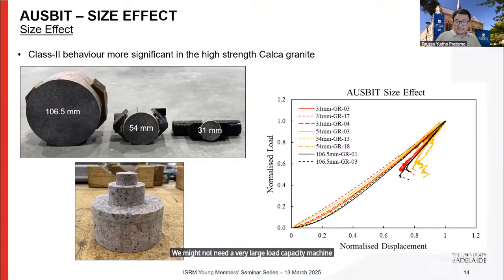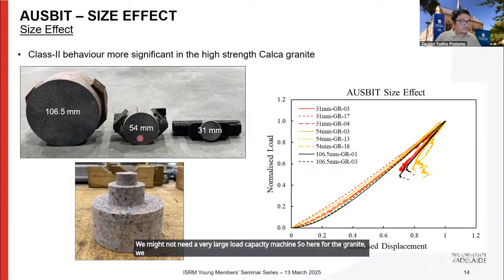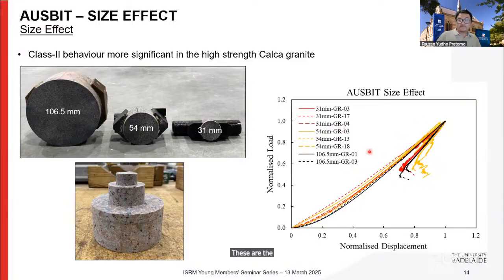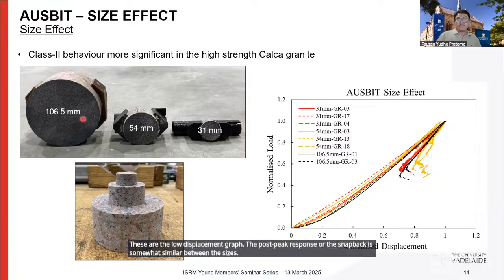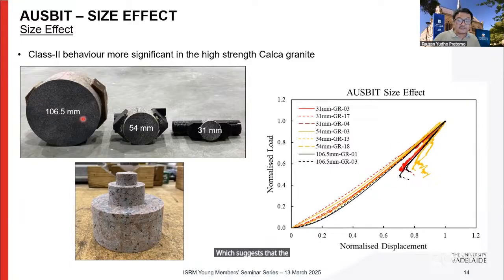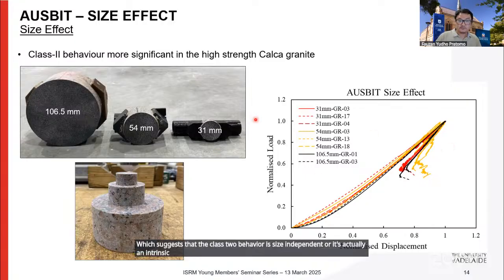So here for the granite, we investigated 31, 54, and 106.5 millimeter diameter specimens. These are the load displacement graphs. The post-peak response, or the snapback, is somewhat similar between the sizes, which suggests that the class 2 behavior is size independent, or is actually an intrinsic material behavior.